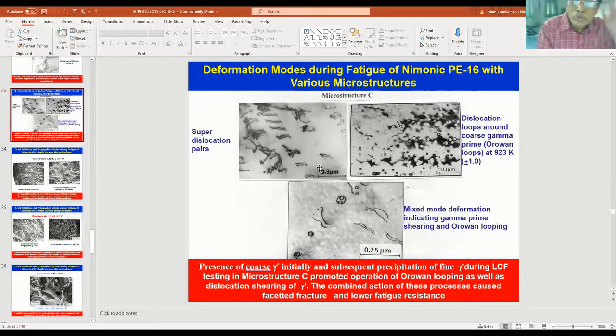Then if your heat treatment is such that the full potential of precipitating gamma prime is not there, some gamma prime can precipitate during service, and then shearing of the precipitate can happen. And owing to the distribution of the particles, we cannot say this is always the critical size. So there will be some distribution. Some coarse particles in the same structure get looped, like what is there here, and some of the fine precipitates get sheared, and then mixed mode deformation will be there, indicating gamma prime shearing and Orowan looping.